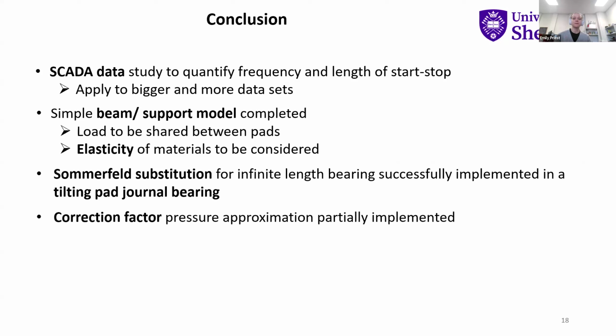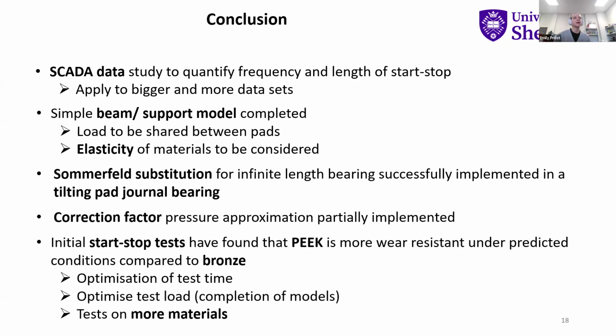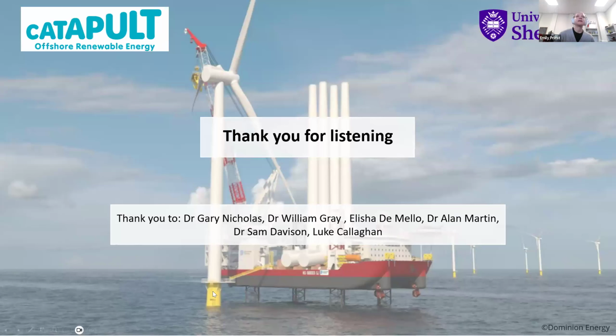got a pressure profile. We've also conducted some initial start-stop tests, and we found that PEEK is more wear resistant under predicted conditions compared to bronze, but we want to optimize the test time using SCADA data. We want to optimize the test load by completion of the models, and we want to test on more materials. So yeah, that's everything from me. So pass it on now.